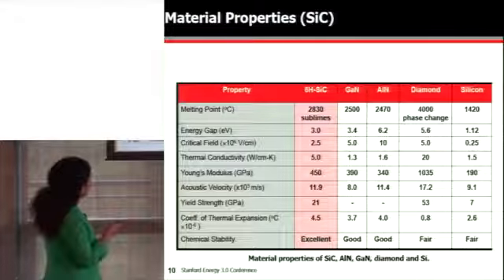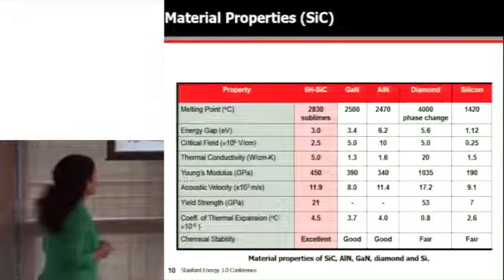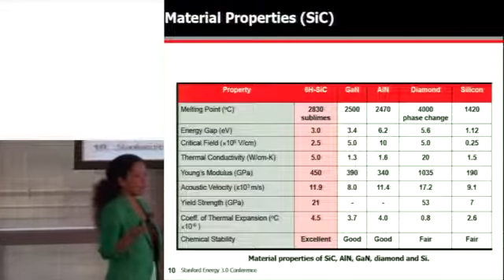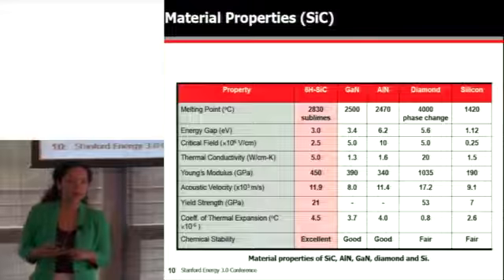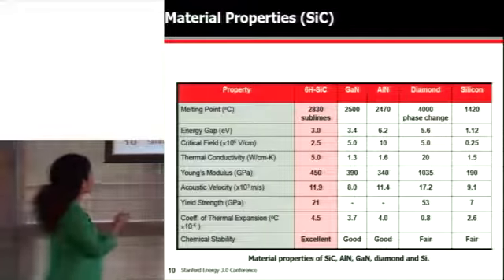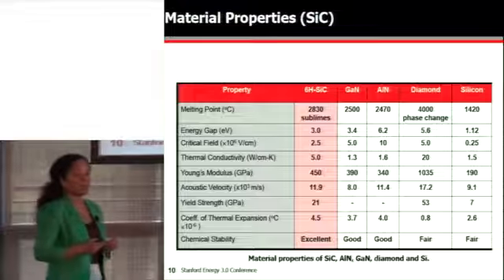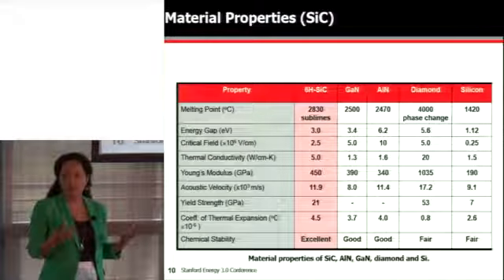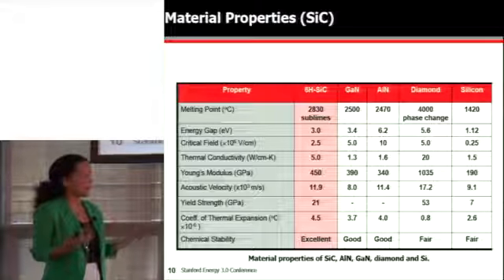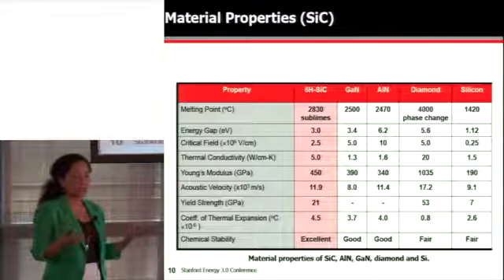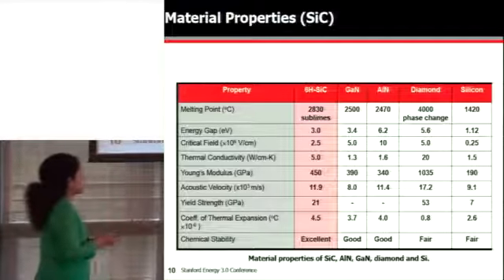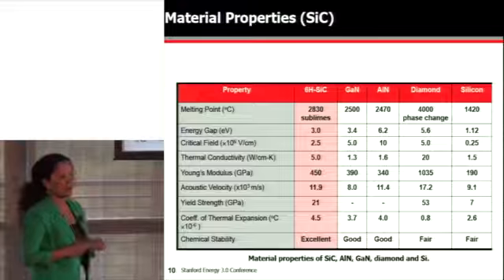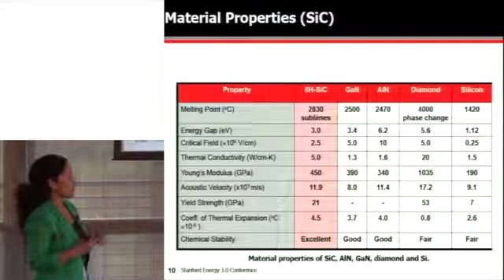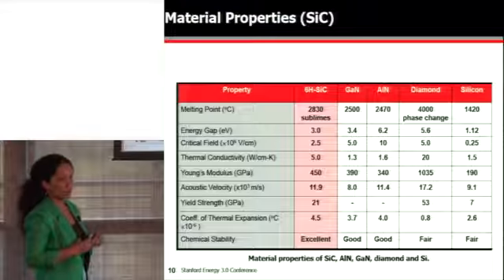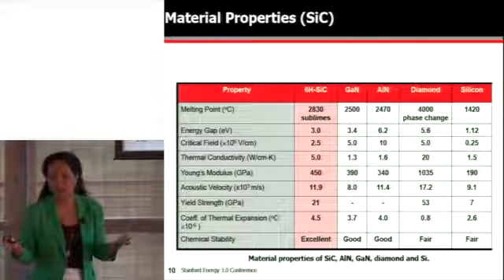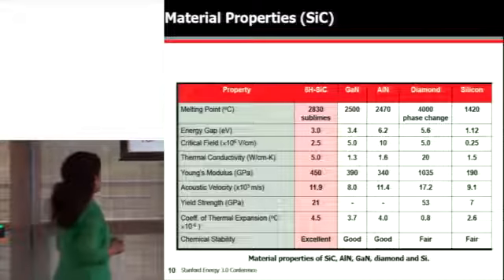So what stands out to me is, number one, the sublimation point at 2800 degrees Celsius. So this is thermally a very, very robust material. It takes a lot of energy to break apart the silicon and carbon atoms. Also, the energy band gap stands out to me at 3.0 eV. That corresponds theoretically to a temperature limit of 1,000 degrees Celsius. So you can have a transistor theoretically operating at 1,000 degrees Celsius, whereas silicon, the band gap at 1.12 eV, corresponds to a temperature limit around 250 degrees Celsius. So your cell phone most likely wouldn't work at 250 degrees Celsius.